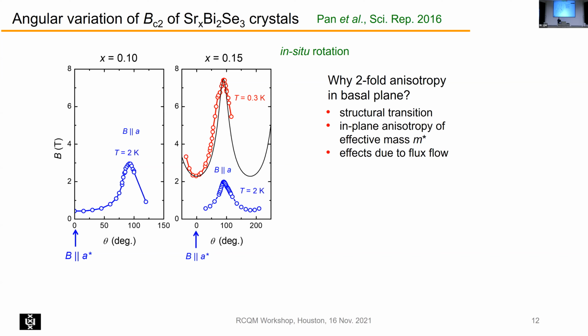And particularly you can have an active flux flow, because if the current and the field are parallel, you have no flux flow, and if they're perpendicular, you could have flux flow. Well, we can already argue from our data that that's not important, but we also did an experiment where we have the current flow along the z-axis, and then we rotate in the plane, and then you can actually really take this effect out. So it is not due to these effects.